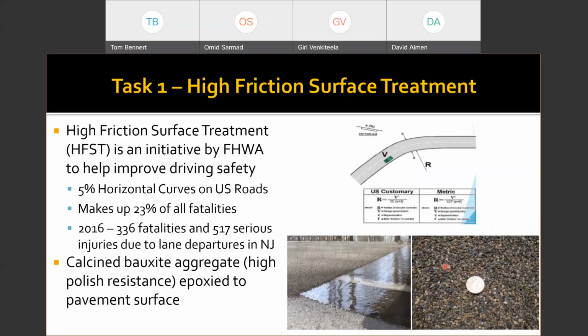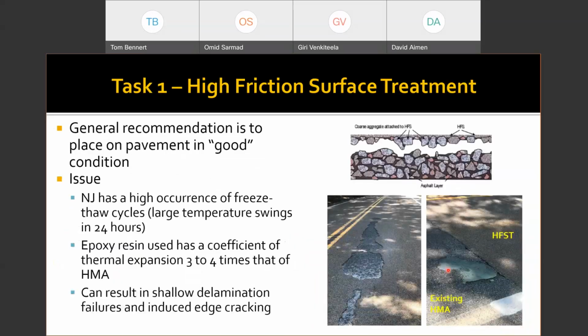It can be a little bit of an expensive treatment. The aggregate is very expensive because it's a bauxite stone, but then it's superheated to create the hardened effect that gives it its hardness. It's very angular on its own, but they go ahead and process it to harden that material up. There are some other specifications that go along with it. It has to maintain a certain skid resistance. But when you go through the general design process, the recommendation is to place it on a pavement in good condition. The problem there is, what is the definition of good?